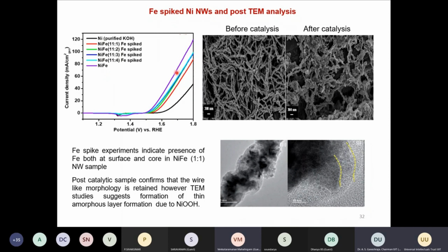So this basically tells us that the activity of the nickel iron nanowire which we prepared previously is better than this activity. That clearly indicates that iron is not only present on the surface of these nanowires, but also present at the core of these structures.